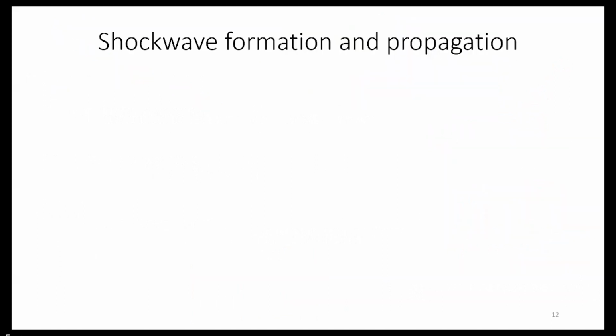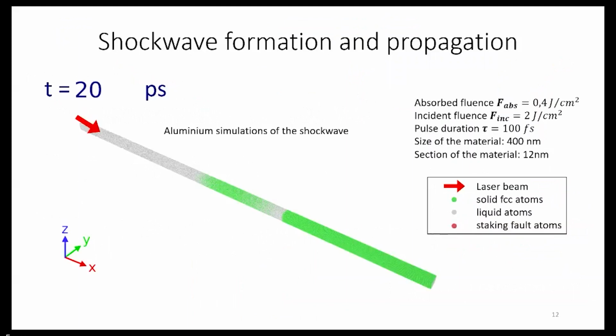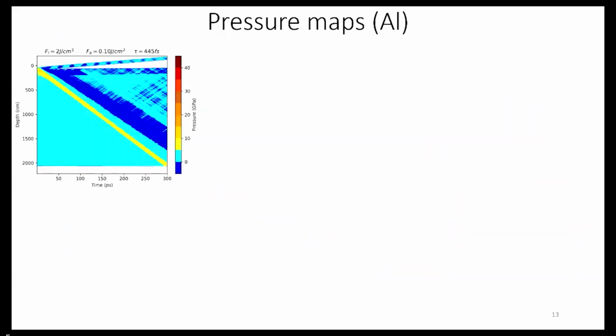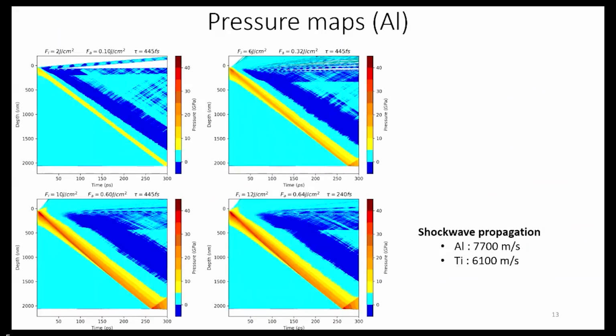Here's a picture of what we can get from the MD simulations, where you can see the laser is coming from the red arrow, and then we can see that with different time delays, some of the solid FCC atoms become liquid, and then when they become solid again, some stacking faults remain, meaning that there is creation of dislocations. And then we can also compute some pressure maps.